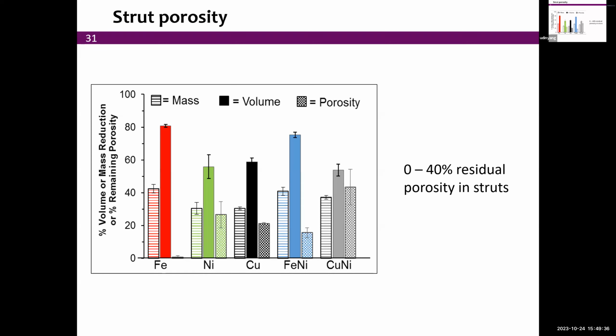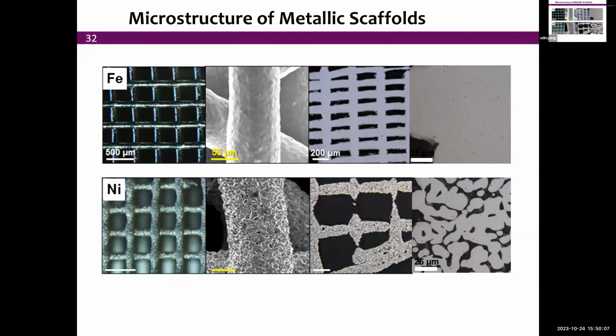So here's iron, with very large shrinkage and zero residual porosity, so the struts are dense now. At the other extreme, here is, for instance, nickel, which still has about 30% residual porosity. So that's interesting. It means that depending on the level of sintering, we can maintain some extra porosity within the struts, which would further make it lighter. Or vice versa, if we want something strong, we may want to sinter the material completely and not have residual porosity.